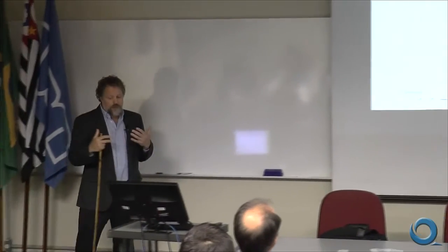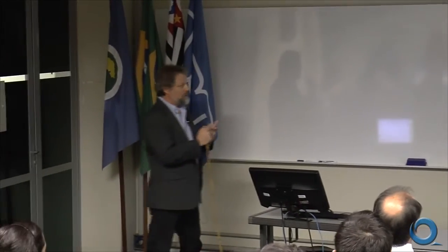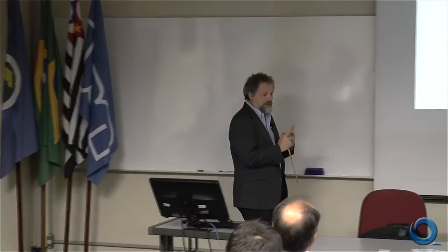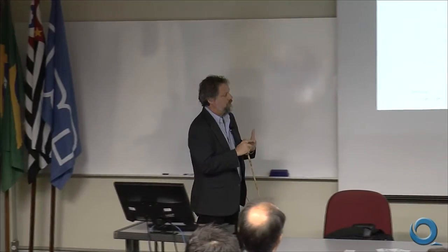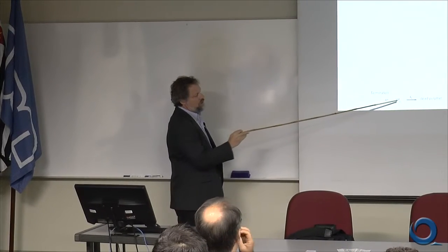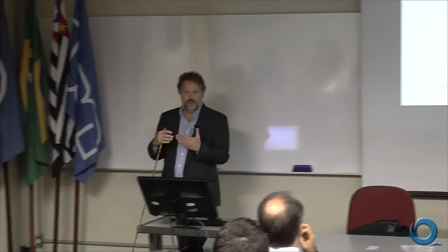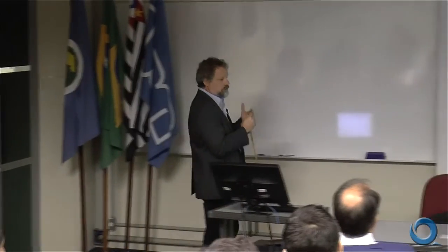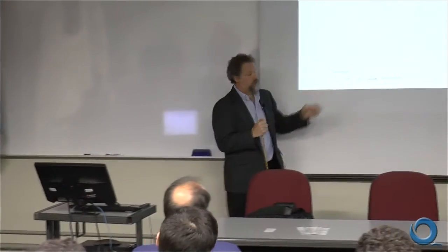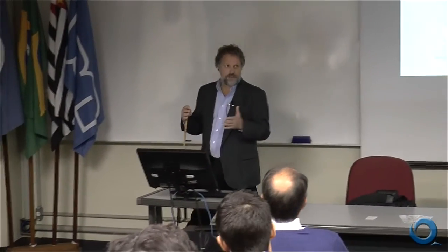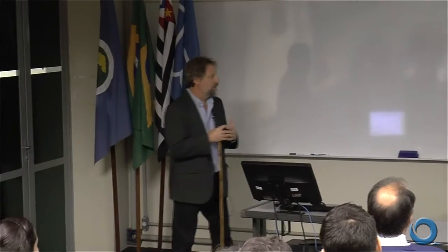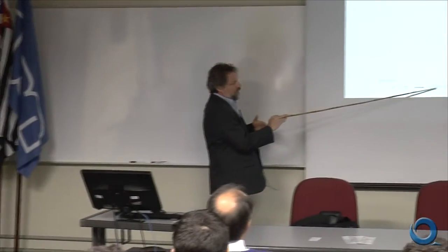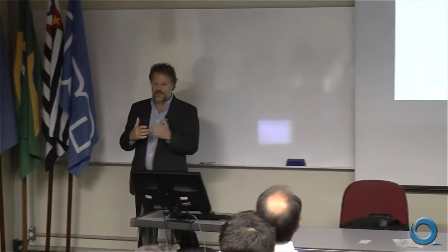The problem with this approach for us is, first of all, that you tend to get very polydispersed polymers. So there's no controlling when these two growing polymer chains will find each other. So we might find short chains reacting to form a small polymer or longer chains reacting to form a larger polymer. And so you get a very polydispersed mixture of many different molecular weights. The other problem is that it is in fact a dead polymer. So we can't use that to make a block copolymer like we want, because we cannot reinitiate the polymerization.